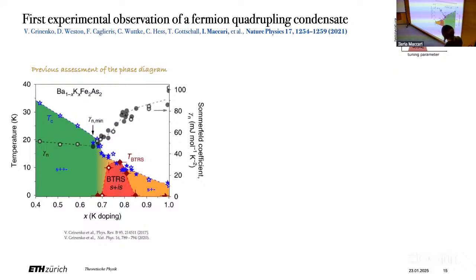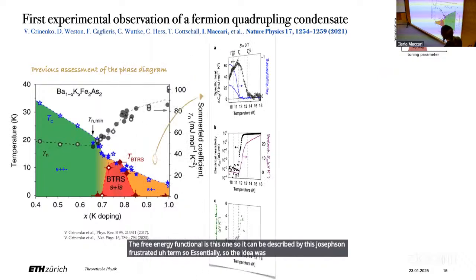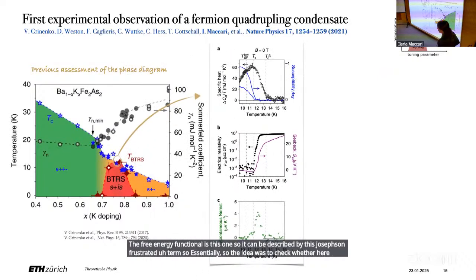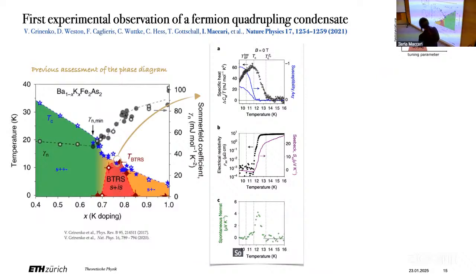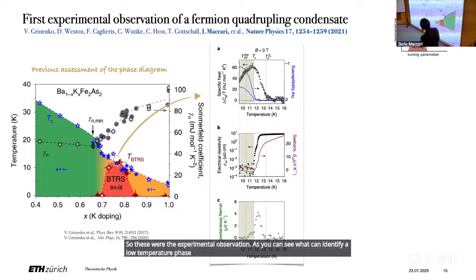Essentially, the idea was to check whether there could be some splitting of the two phase transitions, so if the two occur together or not. So these were the experimental observations. As you can see, one can identify a low temperature phase where the system has a Meissner magnetic response, this blue curve, the Meissner effect. The resistivity is zero.